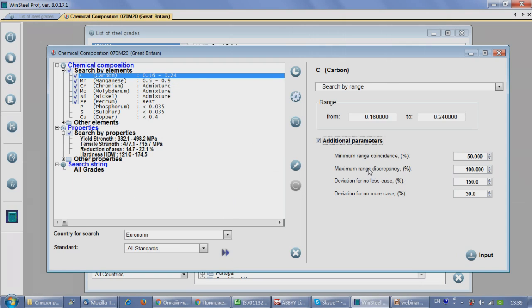This is the maximum range discrepancy. This coefficient is used to differentiate grades, for example, 304 and 304L. These are stainless grades, with a carbon content in 304 of 0.08, but a carbon content in 304L of 0.03. So to differ these grades, this second coefficient is used.